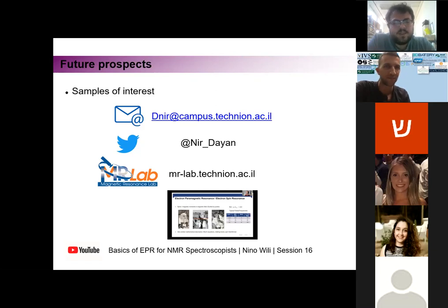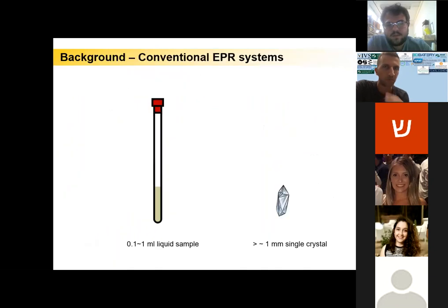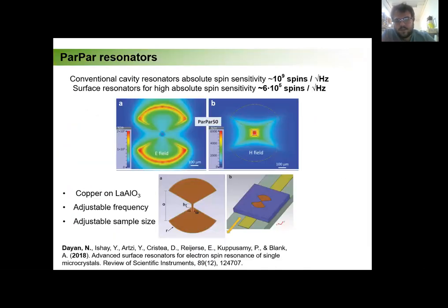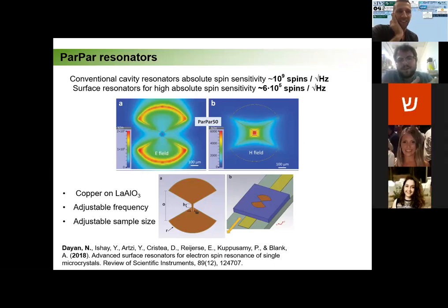And it's more challenging to couple my resonator to my device, because as I showed here, the location of the resonator with respect to my system is very crucial, and it's one of the most difficult parts of the experiment. If I try to irradiate with, say, 35 gigahertz, it actually has to reach the resonator, and sometimes the resonator, the little bridge there, has to be really aligned. Yeah, that's pretty much our problems. So with the superconducting, we can stay at the same sizes, but we get higher sensitivity.